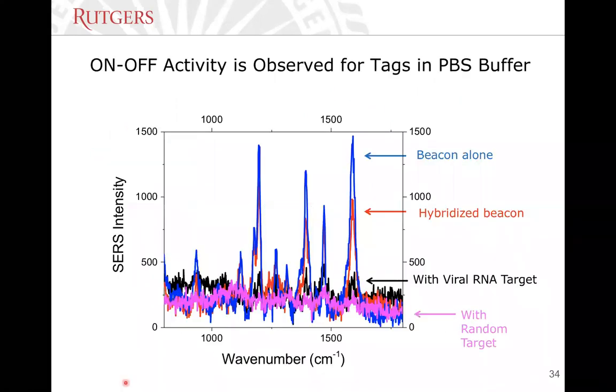We're studying buffer first. We see here when the beacon alone is folded, the SERS signal is on. We hybridize it, sorry, this is actually mislabeled. We hybridize it in black here with the beacon, right? And it quenches, so when it opens up. And eventually we expose it to the RNA target in red, and I'm sorry for having confused you, and we see a recovery of the signal. So what you can see is that we go from on to off to on again, as I was telling you before. The recovery of the signal is not entirely 100% perfect because we believe there are some steric hindrance issues at play that we're currently investigating.